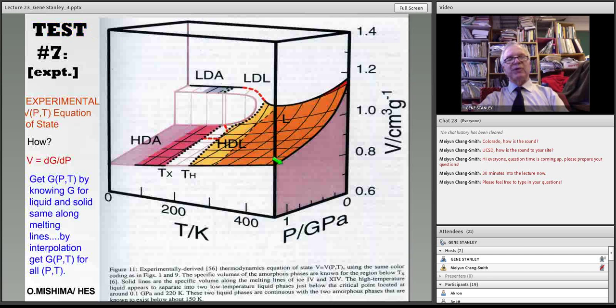But the Gibbs potential for the ices has been tabulated. So we end up knowing the Gibbs potential of the liquid. And when you know the Gibbs potential, you can differentiate it and get the volume. And therefore you have the volume, which is shown on the y-axis here, as a function of temperature and pressure. And this is the so-called equation of state. Here's our low-density liquid, high-density liquid, low-density amorphous ice, high-density amorphous ice. And here's the critical point, a hypothesized critical point, where there's no more a difference between the two liquids, LDL and HDL. This is also Mishima's work.